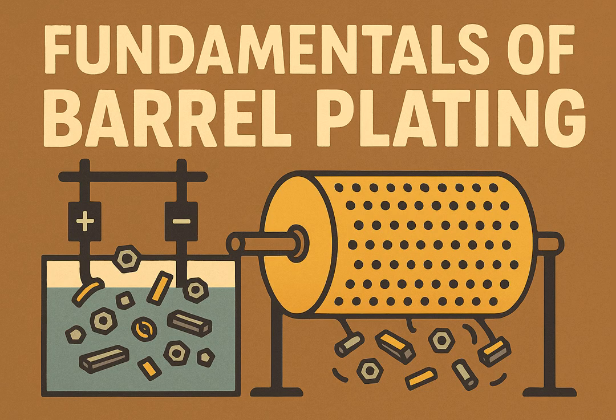Those tiny voids or pinholes in the deposit can be caused by organic contamination or oil in the bath, trapped air bubbles due to insufficient mixing or poor part geometry, inadequate pretreatment, metal impurities in the bath, or chemistry imbalances like low boric acid content or low bath temperature. Lots of potential causes for pits. Yeah. Solutions involve diligent filtration, proper agitation, bath maintenance, and strict process control.